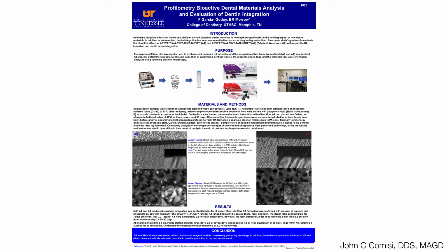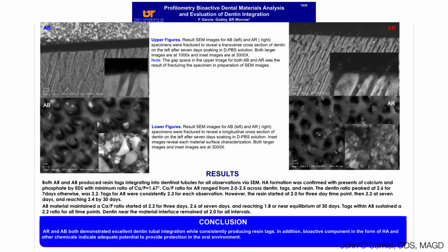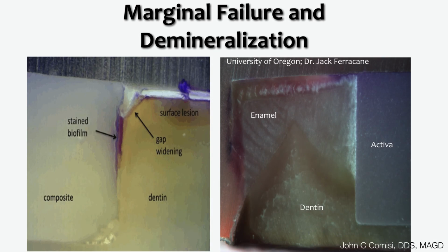Franklin Garcia Godoy presented this poster at AADR last year and shows the tubular integration and apatite formation with Activa base liner and Activa restorative material. So there's something going on with this material, and I believe that this is a new generation and revolution that's going on. The University of Oregon marginal failure and demineralization studies also included Activa in the process, and it shows that the Activa material under the same test results shows high integrity and no marginal leakage, demineralization, or failure when compared to the other materials tested. And again, this should be very interesting to everybody as you work with and review and work on finding out more about this material.